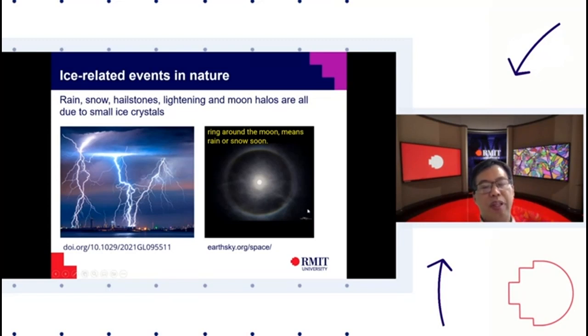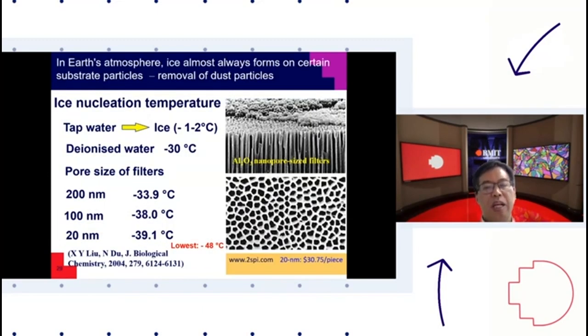So the small ice crystals, or the solidification of water, is very important. Given my time, I'll quickly finish this one. Tap water contains many particles, millions of very small particles, down to the nano size. Deionized water has had a lot of impurities and small particles removed. For tap water, ice crystallization, the formation of ice, would probably happen at -1 or -2 degrees. And this is about -30 for the deionized water.